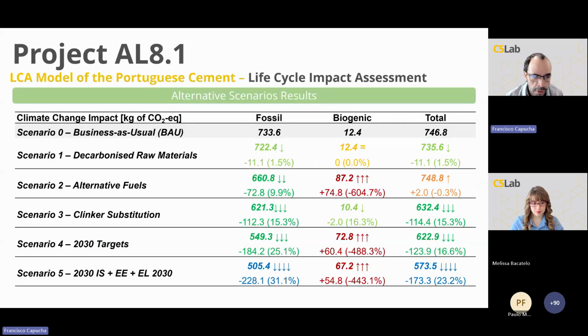So we introduced this data into the new model, and the results for the alternative scenarios based on industrial symbiosis showed that the use of alternative raw materials and clinker substitution resulted in a reduction of carbon emissions. However, the use of alternative fuels led to a slight increase in emissions. This was unexpected, and this increase was due to the fact that at the time, the modeling technique accounted for the biogenic emissions, so they contributed to the environmental impact. And this is not currently used in cement manufacturing life cycle assessment models. Therefore, the results will be a bit different nowadays.